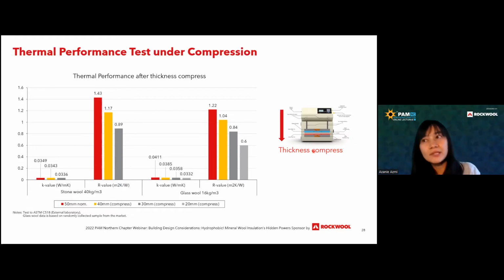You can see here the two samples that we sent: the first one is Stonewool 40 kg and the other one is Glasswool 16 kg. You can see that the K value changes slightly, but the R value, because the thickness is compressed, will be affected. It will become lower. So actually it's not good to compress it if you want to comply to a certain U value performance. For this Glasswool, because of their very low density, they are easily compressed with tests up to 20 mm thickness. As you can see here, performance of the insulation will decrease.